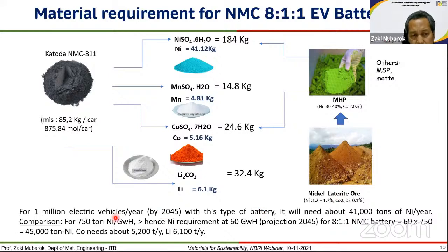And if I calculate also from the criteria that it requires, the battery requires 750 ton nickel per gigawatt hour, then the nickel requirement at 60 gigawatt hour, this is projection 2045, the number is not much different with the number which is calculated from stoichiometric requirement of nickel, cobalt, and manganese. Yeah, it requires 45,000. And the requirement of cobalt and lithium are about 5,000 and 6,000 respectively.